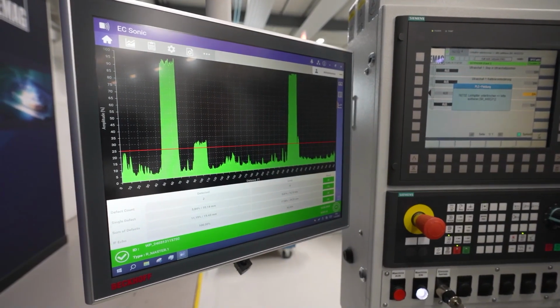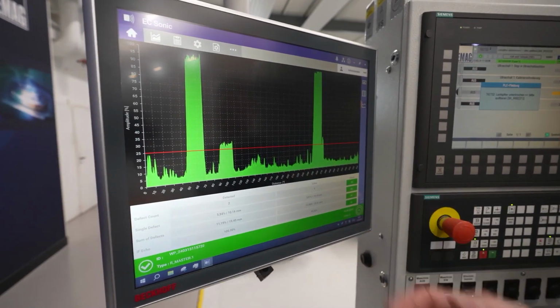Single defect was maximum 5.87 allowed. We have just below 5.84, so okay. And the sum of defects can be up to 17%. In this case, only 11, so okay rated.